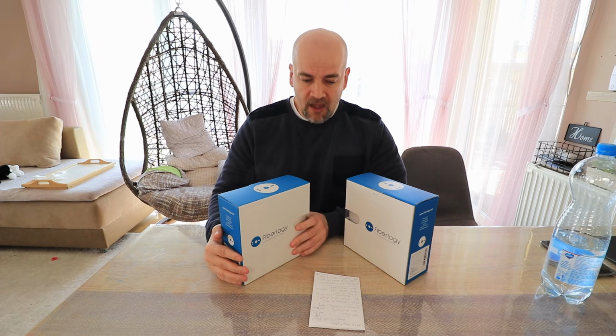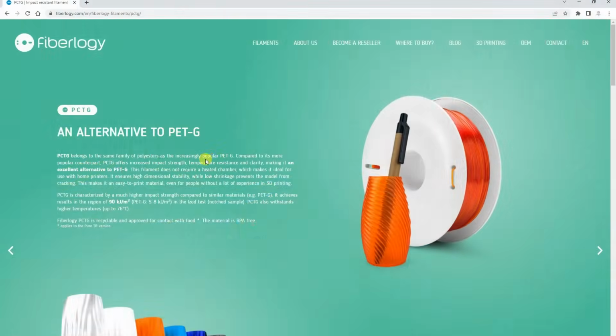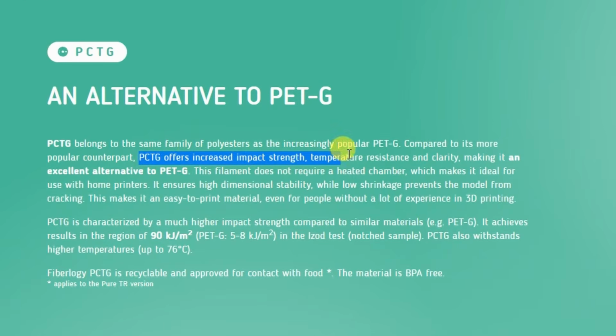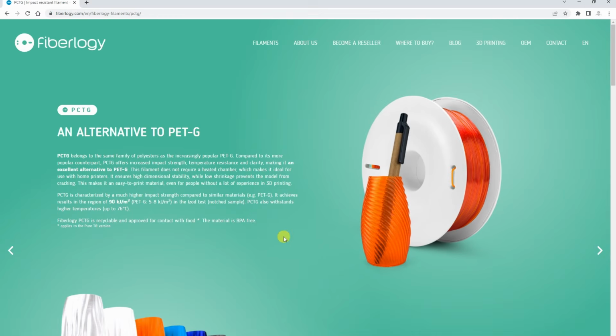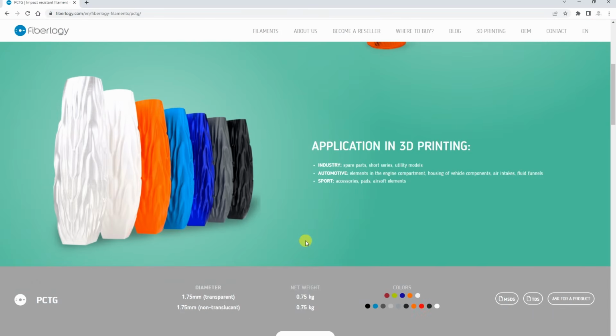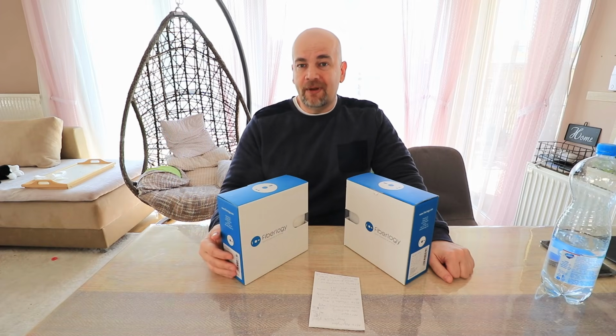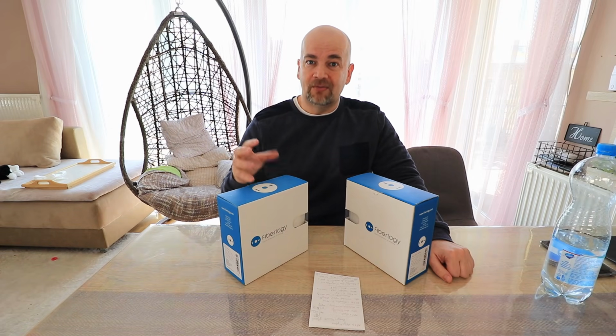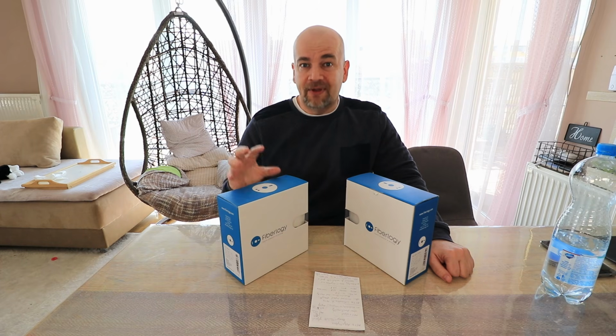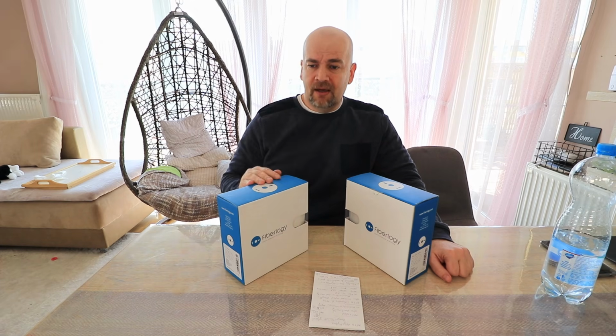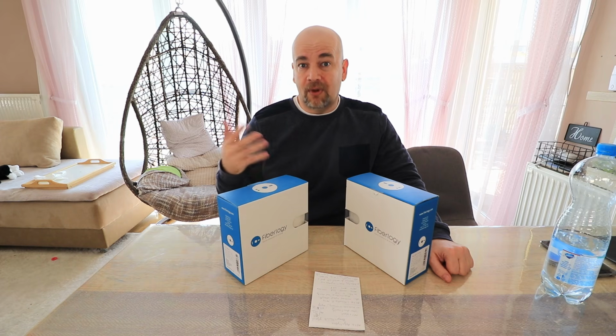About PCTG, it is a great alternative to PETG, and it offers increased impact strength, higher temperature resistance and clarity. Now about its impact strength, according to the website, it has 90 kilojoules per square meter impact energy, and compared to PLA it is 10 times stronger. If this is true, probably this will be the second filament which will not break on my Izod impact test, where I'm using the half kilogram hammer, so I have to raise it a little bit higher, or maybe I have to switch to the 1 kilogram hammer.